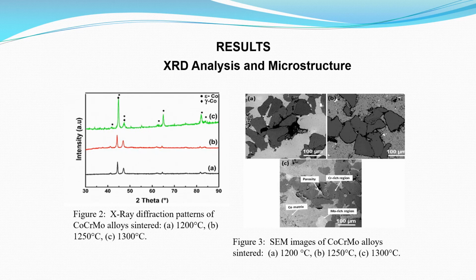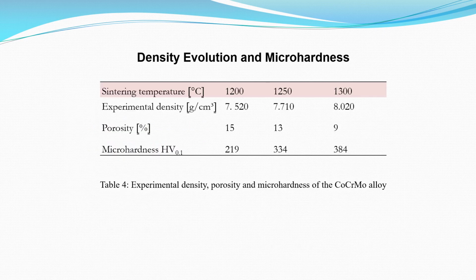In terms of the obtained results, Figure 2 depicts the X-ray diffraction patterns of the samples sintered at different temperatures. Also, some micrographs of these samples are given in Figure 3. And the following table lists the experimental density, porosity, and microhardness of the ternary alloy at the chosen temperatures.